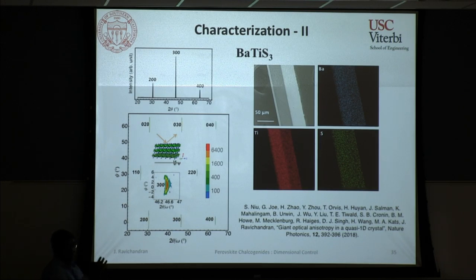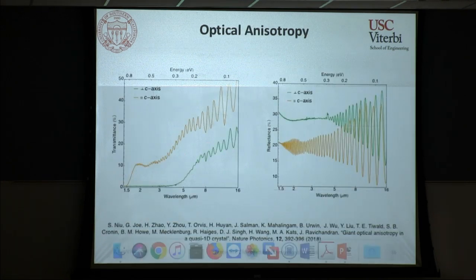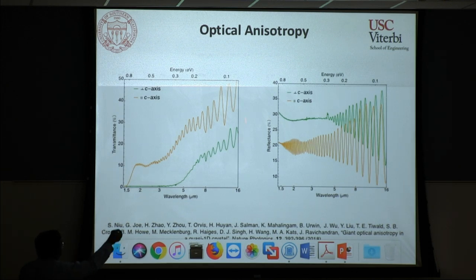So this allows us to completely figure out what the crystallographic axes are in your crystal itself, and that way you can tell what the 1D chain axis is in your system. Okay, so of course we also checked the chemical composition and purity of the system, and with this information we started looking at FTIR spectroscopy to look at the anisotropies in the system. So this is the FTIR spectroscopy for your polarization aligned parallel and perpendicular to the C-axis, which means parallel and perpendicular to the chain axis.